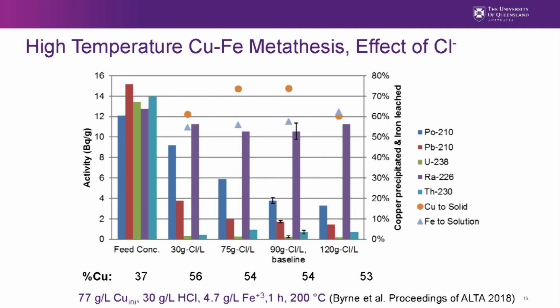Should have started with this, but the feed solution going in was 77 grams per liter copper, 30 grams per liter hydrochloric acid, and the chlorides were topped up here by adding sodium chloride, 4.7 grams per liter ferric, and 1 hour, 200 degrees. And these baseline conditions were selected to be somewhat similar to an example in the pad. So that's the effect of chlorides on high temperature metathesis.